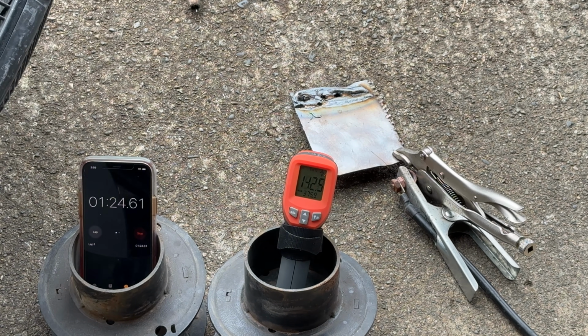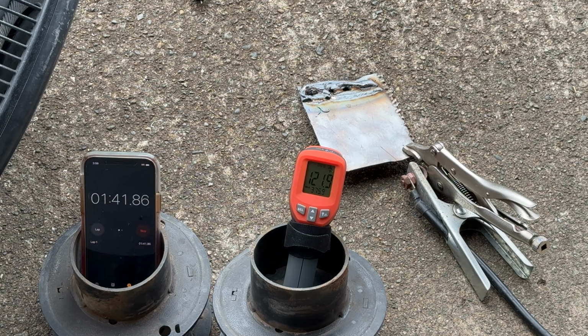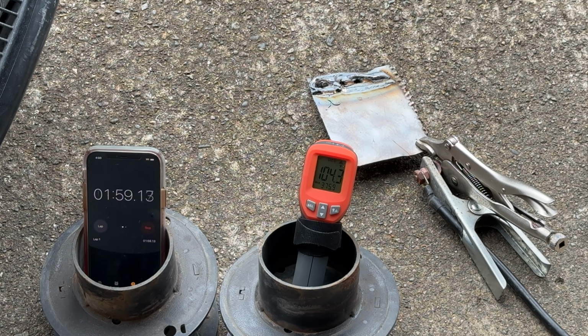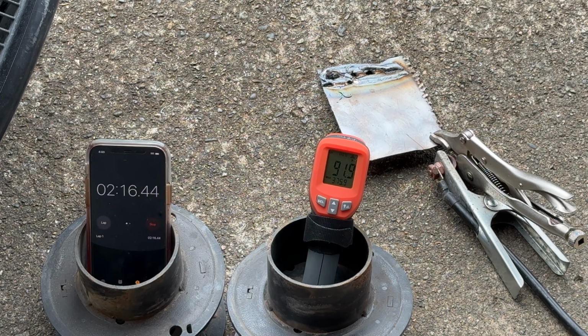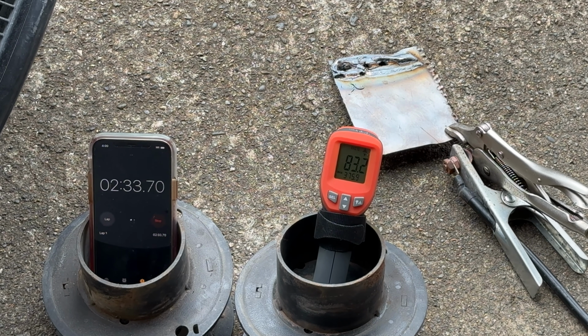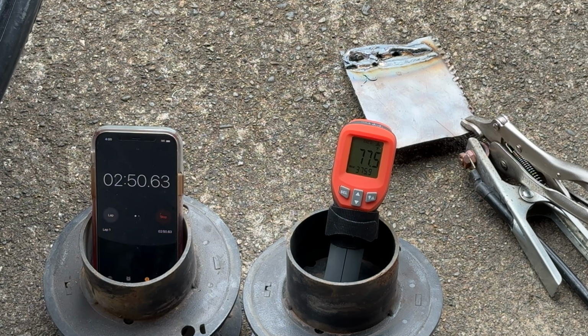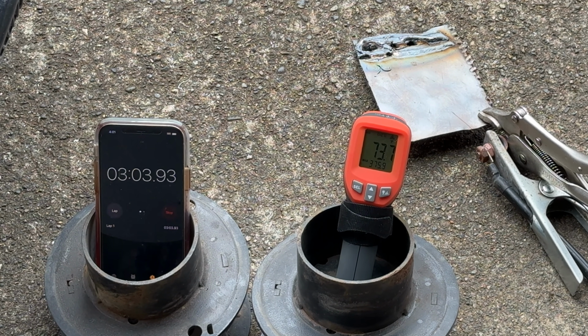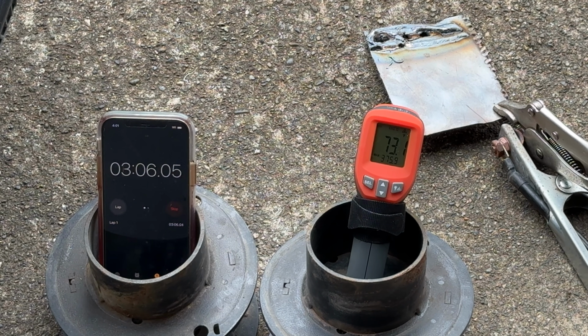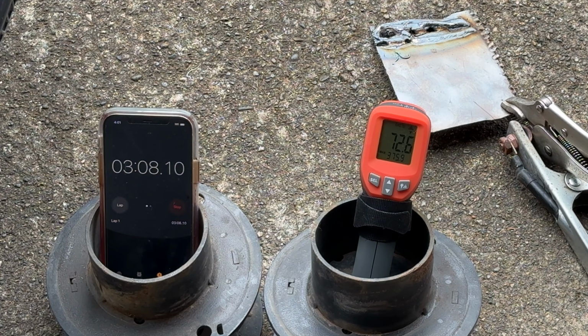That moving air was able to move the heat away from the panel a lot more efficiently, and in the end was able to cool this panel down that was already almost 100 degrees hotter than the previous test. It did that in 3 minutes and 5 seconds, which is less than half the time of the previous test.